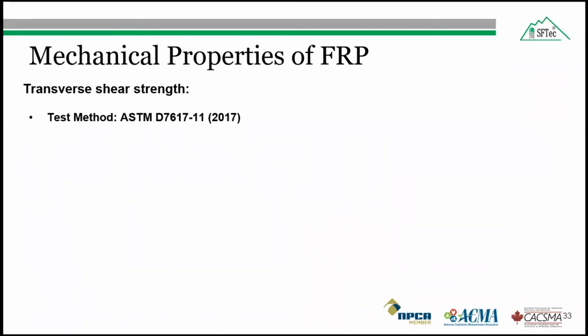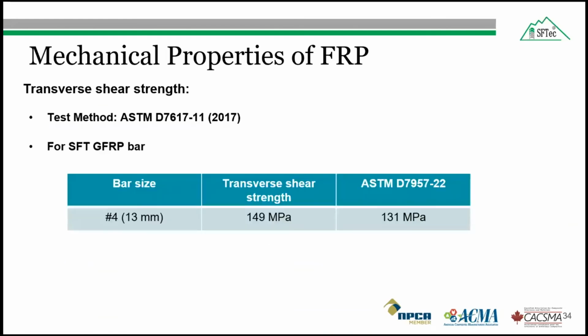So after testing the samples in shear up to failure, the transverse shear strength was calculated using this equation. And in this equation, PS is the failure load in Newton, and A is the FRP bar area in square millimeter. And for our SFTec glass fiber reinforced polymer bar number 4, the average value was around 149 megapascal, which was greater than the requirement in ASTM D7957.